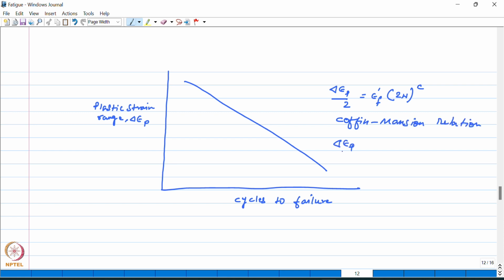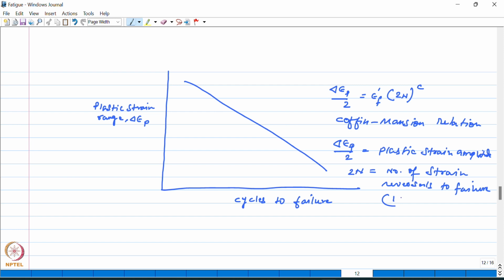Here delta epsilon P by 2 is the plastic strain amplitude. 2N is the number of strain reversals to failure, wherein one cycle is 2 reversals, and this parameter epsilon prime f is known as the fatigue ductility coefficient, and this is approximately equal to the fracture strain for many metals. Okay, so this is how the low cycle fatigue data is presented.